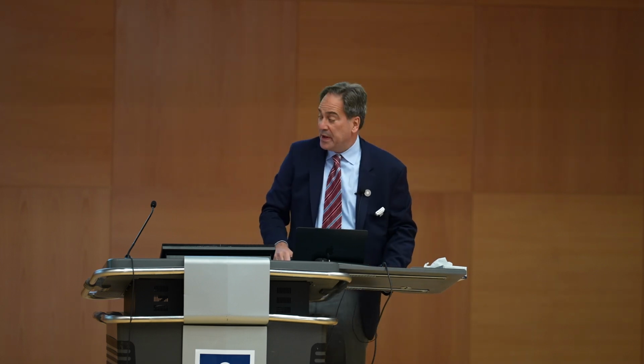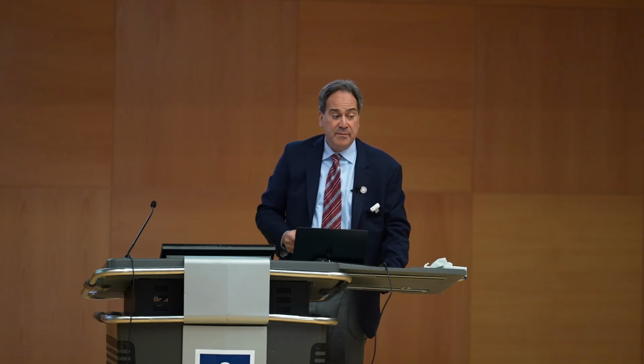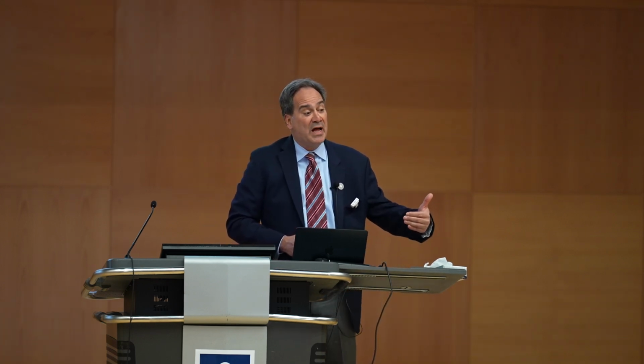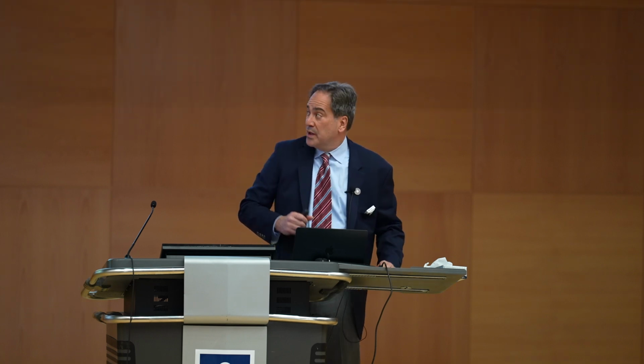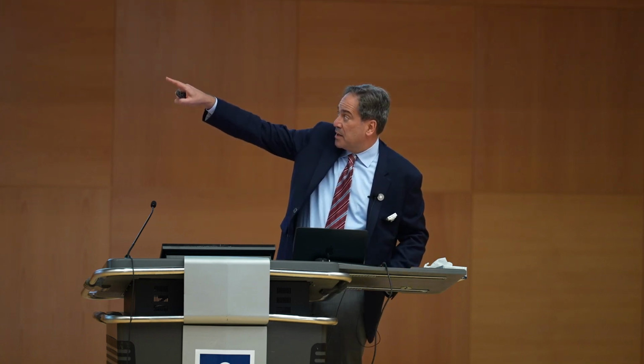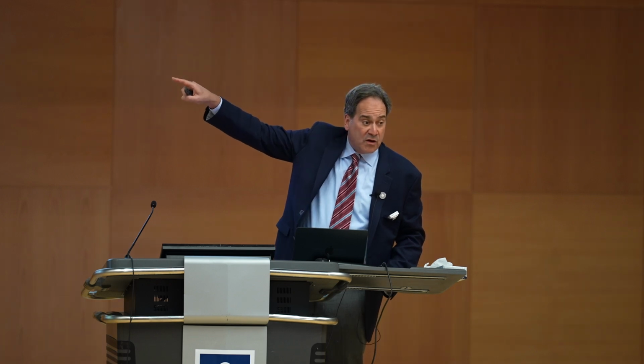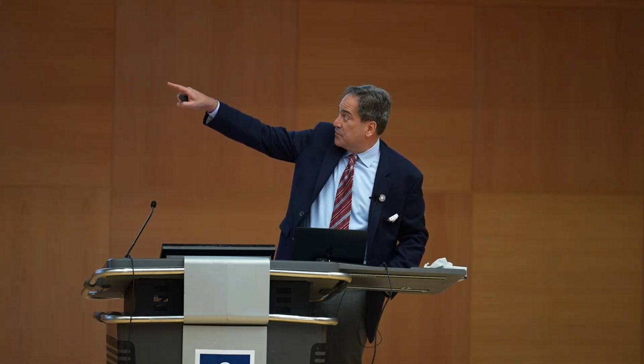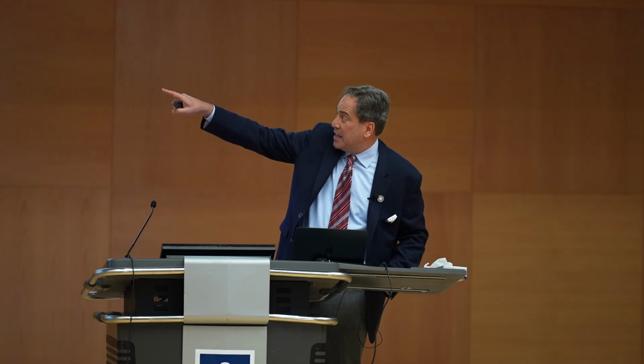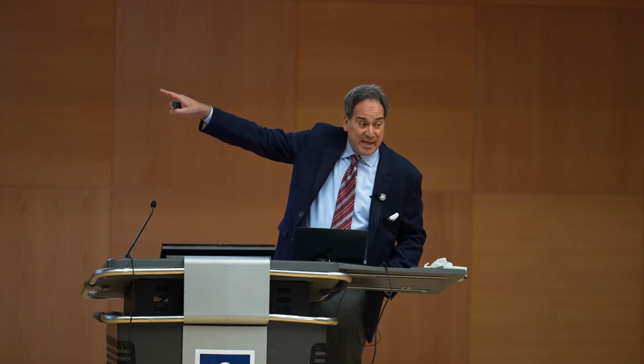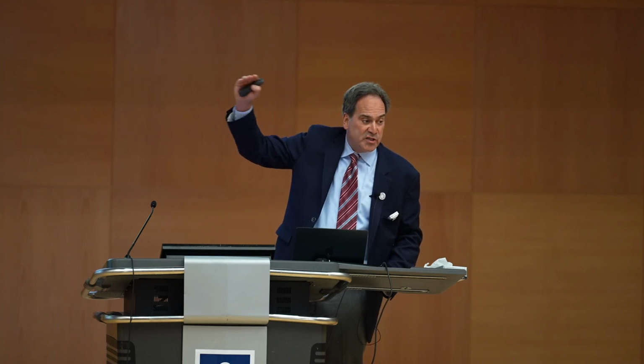And in this game, you're basically trying to beat platinum, or be at least as good as platinum and have less platinum. And so if you look at overpotential, it's plotted in the upper left here, a bar on that graph is not good. And so if you look at this, no big surprise, platinum copper's not good, platinum nickel's not good, platinum gold's not good. Surprisingly, he thought platinum gold nickel was going to be great. That was at the top of his volcano plot. It's lousy. This is overpotential compared to platinum. The other one he predicted, platinum gold copper, is actually as good as platinum.